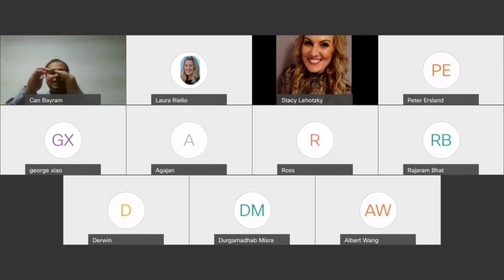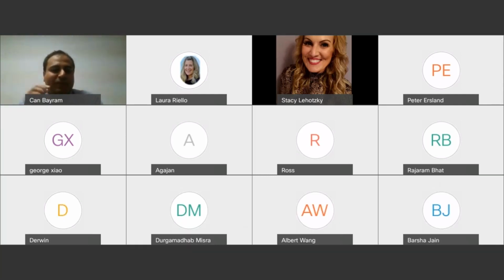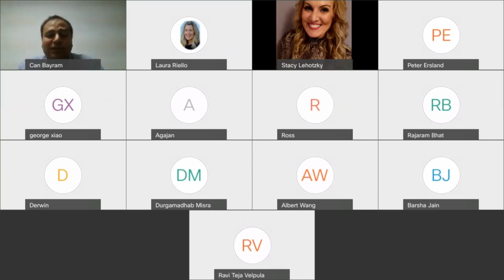The overlayer on top and a combination is going to have, of course, some seam effects when the growth fronts meet, but this is similar to the lateral epitaxial overgrowth that we have done. We do not expect any issues, and the defect density will remain almost the same, except in the seam area where the growth fronts meet. Thank you, Albert.